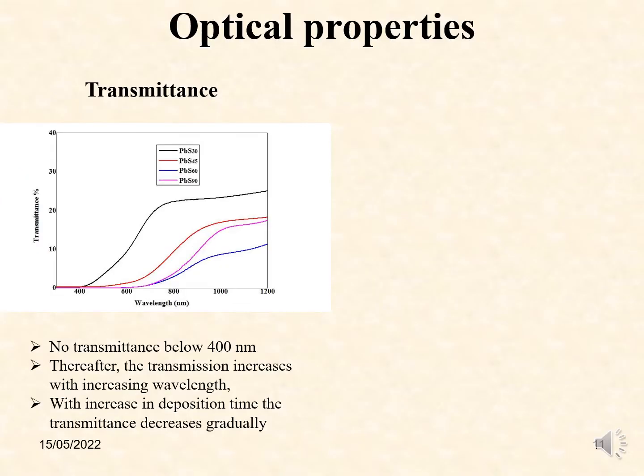Optical properties. Transmittance. We see that there is no transmittance below 400 nanometers. Thereafter, the transmission increases with increasing wavelength. With an increase in deposition time, the transmittance decreases gradually.